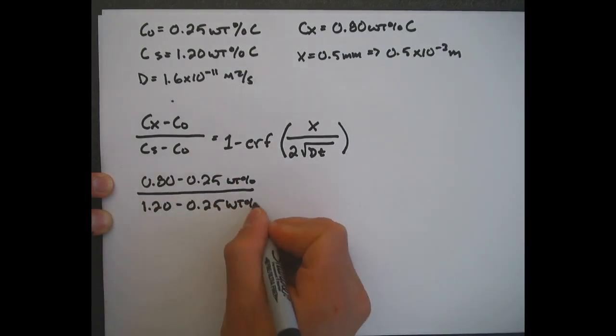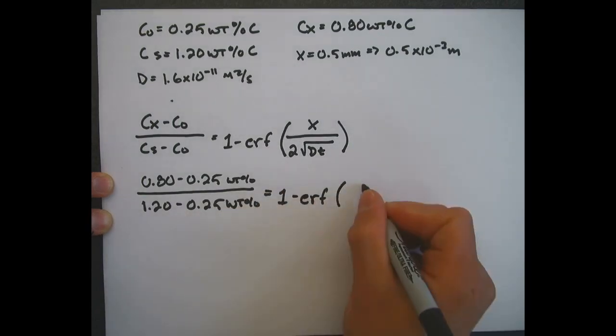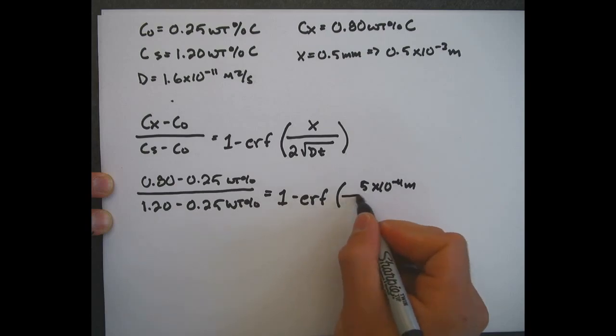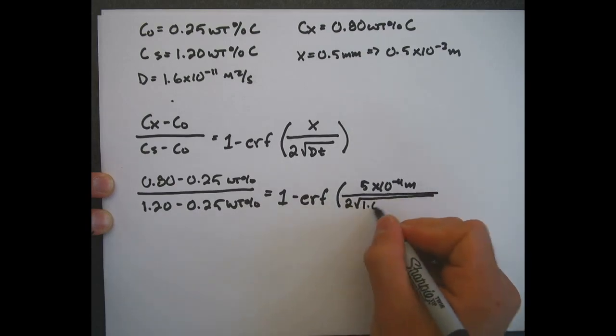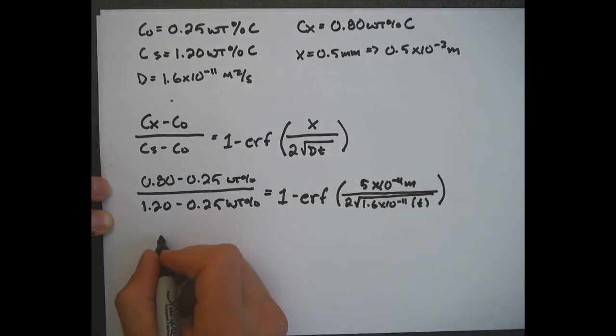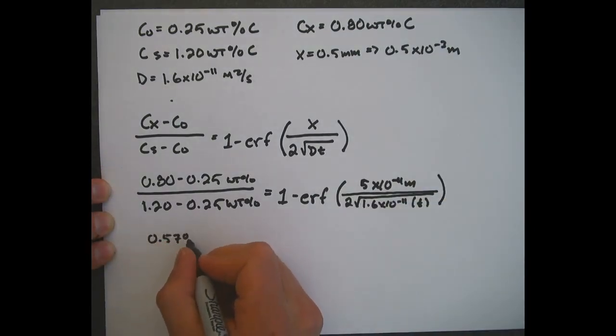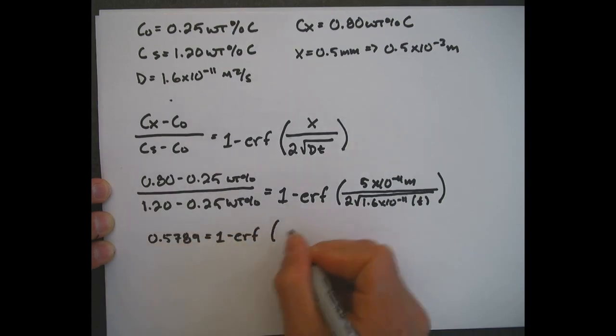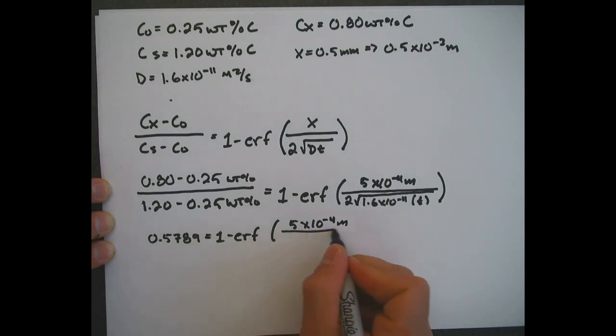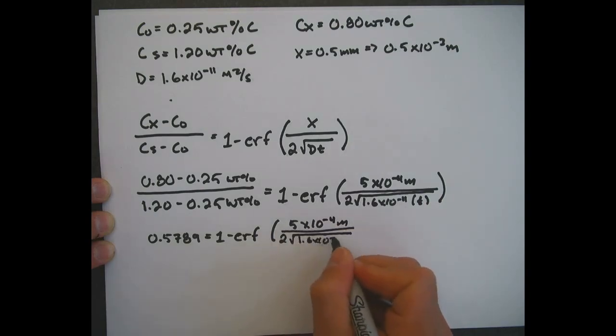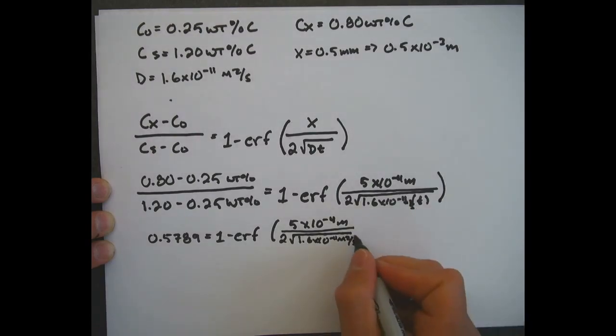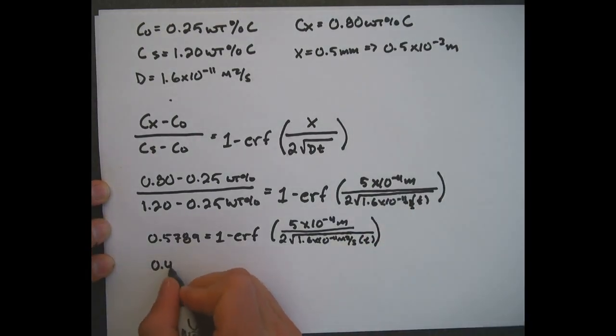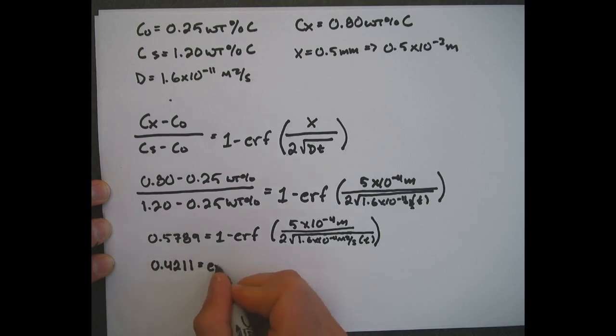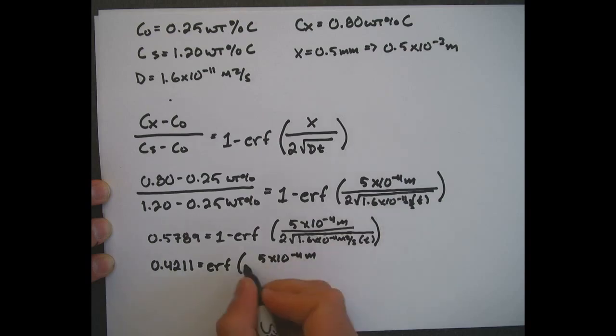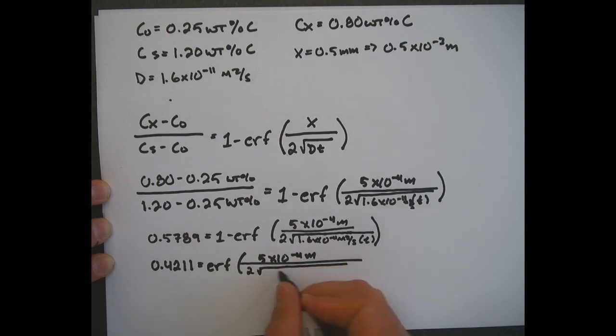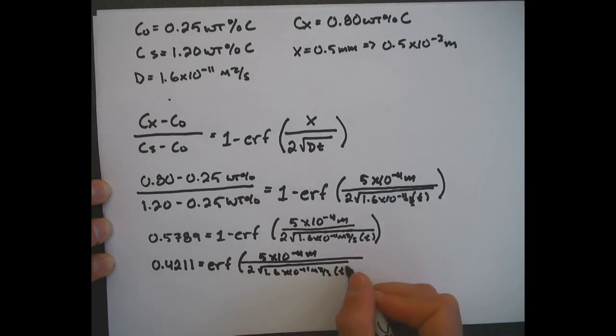So I'm filling in the formula, the error function formula that I've shown you numerous times now, and I'm going to show you how to calculate and solve how long it's going to take for this diffusion with these specified concentrations that we want. So solving on the left hand side, what we get is 0.5789 equals 1 minus the error function of that. Now what we want to do is set the error function equal to a certain value. So solving for the error function, we find that it equals roughly 0.4211.